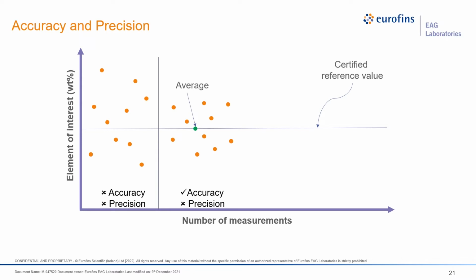The second possibility is where the measurements may have less spread. If we take the average of these measurements, the average would be close to the certified value. This could be a case of having accuracy, but almost no precision. It is important to note that in a real-life example, this is probably the most common behavior observed for measured values.